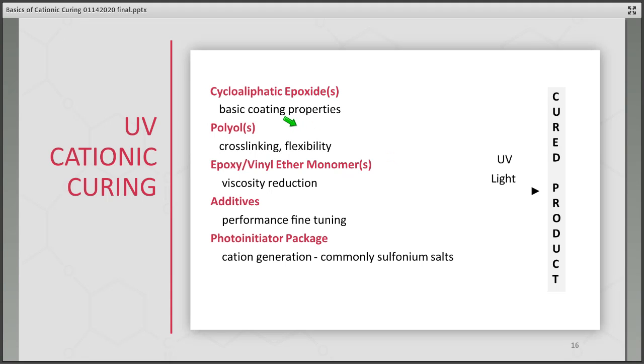And a typical UV curable cationic formulation would look like this. You have cycloaliphatic epoxides. These are the base coating properties. So these give you the bulk of your properties there. You'll have polyols frequently. They will contribute to cross-linking and flexibility. You can use epoxy or vinyl ether monomers, primarily for viscosity reduction, but it could increase the rate, as I will show a little bit later.